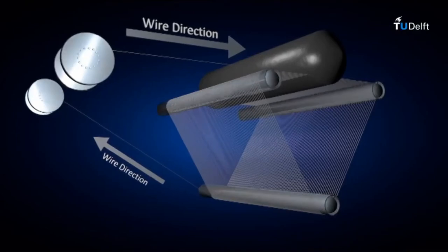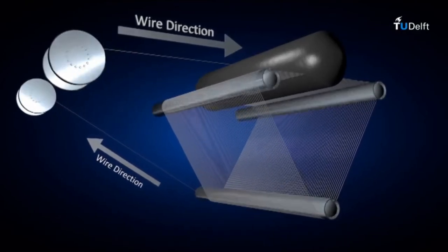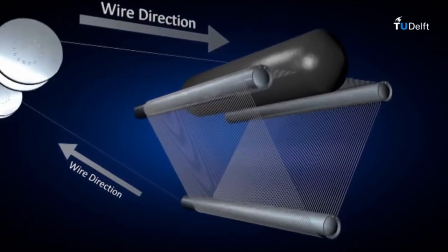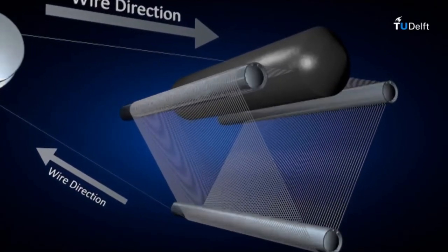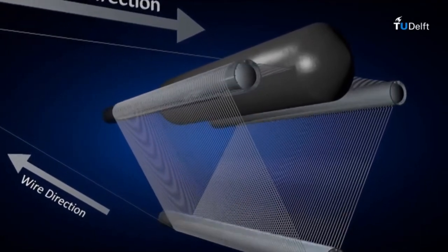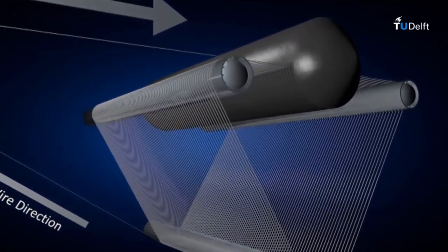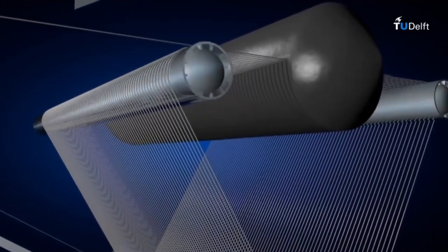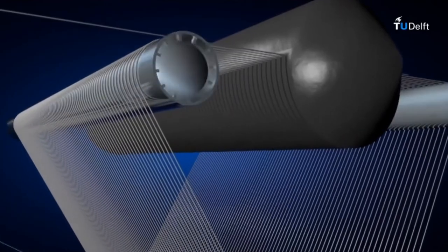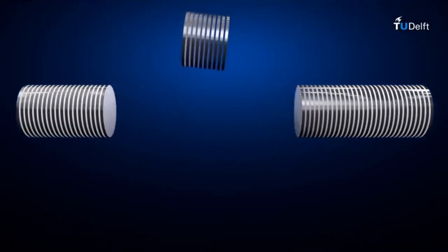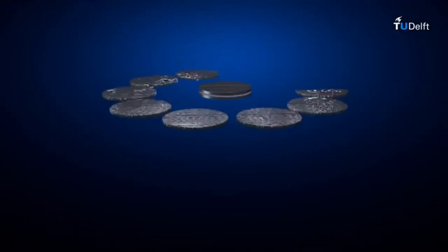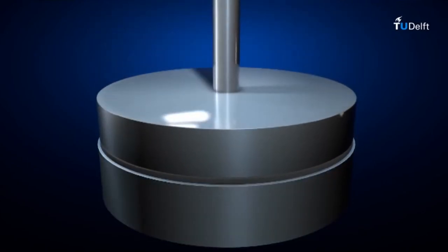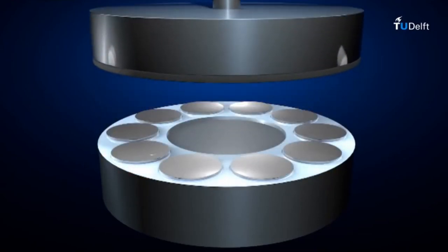A disadvantage of the sawing step is that we waste a significant fraction of the silicon as kerf loss. The kerf loss is usually determined by the thickness of the wire or saw used for sawing and is in the order of 100 microns of silicon. This is a large fraction of the ingot if we consider that typical crystalline silicon wafers used in solar cells nowadays are in the order of 150 up to 200 microns. Sawing will logically damage the surface of the wafers, so this processing step is followed by a polishing step.